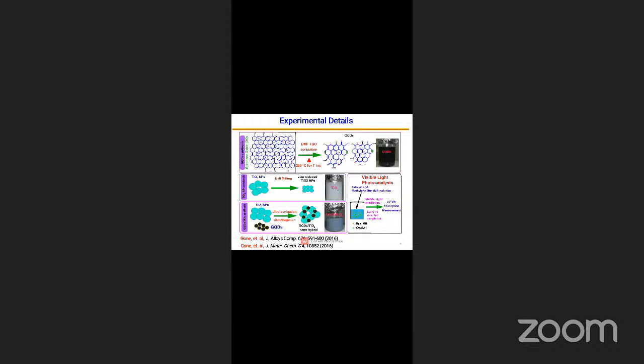So this is the synthesis part. The top one shows the GQDs synthesis, where I have used graphene oxide derived from graphite flakes as the precursor. The graphene oxide is sonicated with dimethylformamide solvent for 1 hour. Then I did the chemical reaction in an autoclave, with the DMF graphene oxide solution at 200 degrees centigrade for 7 hours. I obtained graphene quantum dots with different functional groups. You can see the edge defects.